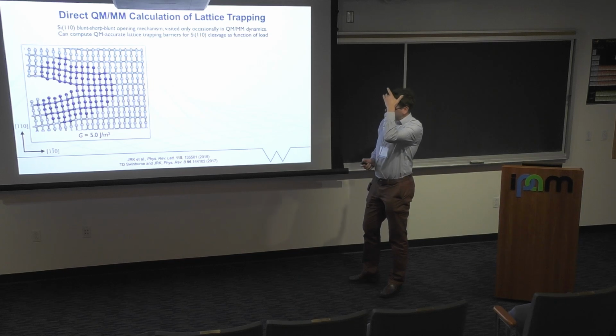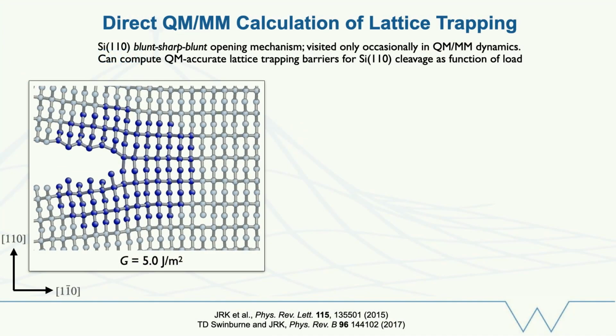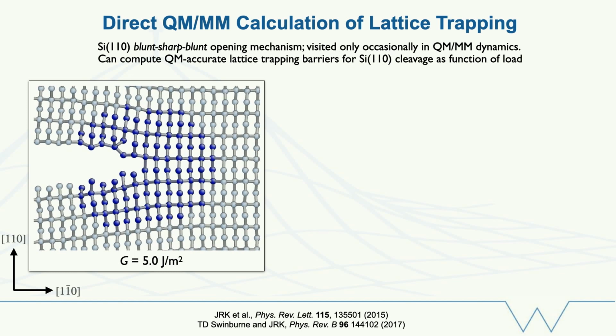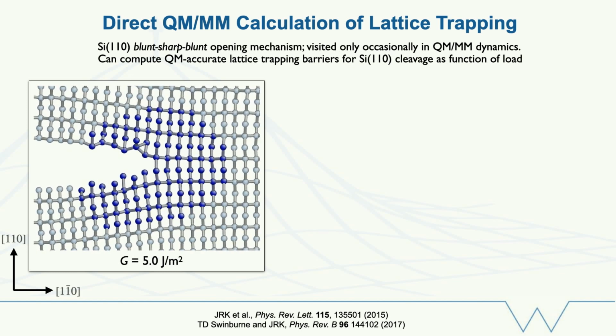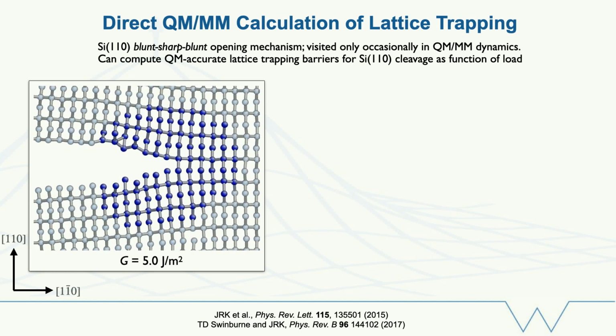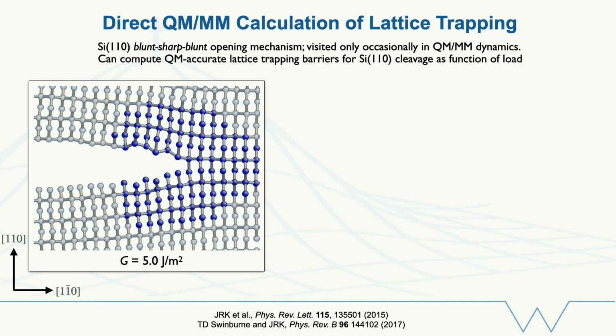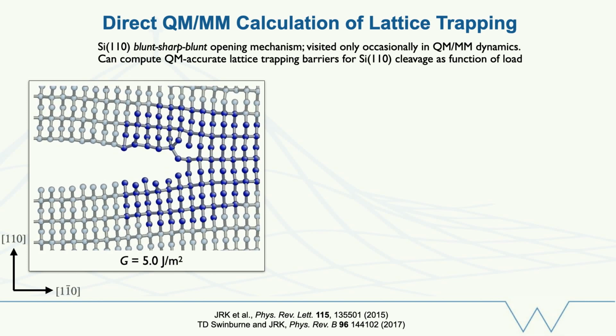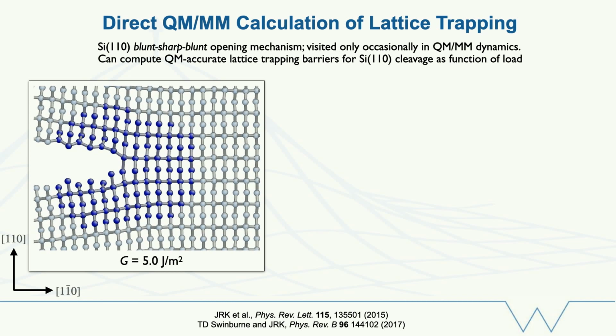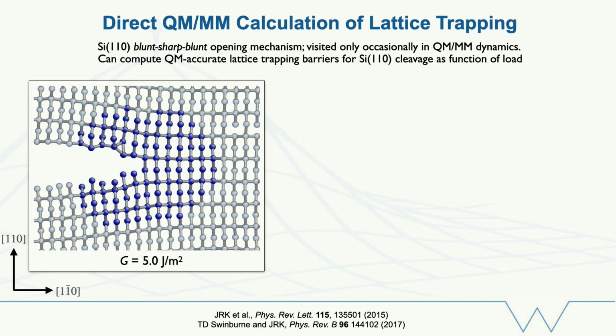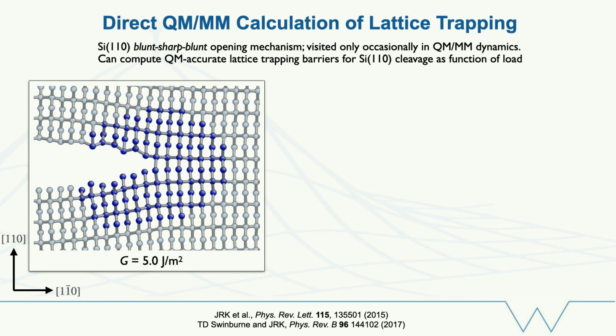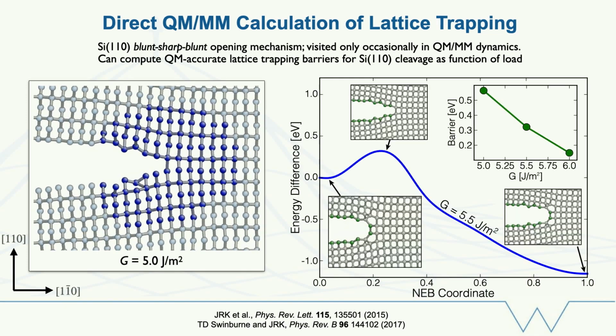So you can do this a little bit with QM/MM. You can do expensive calculations, and this is on the 110 plane in silicon at a lower load than what I showed you before. So the crack is propagating slowly. It's thermally activated fracture, essentially. Every now and again, it gets trapped in one of these sites here, but it's expensive to do that with dynamics, and it's much better to try and directly compute minimum energy paths.